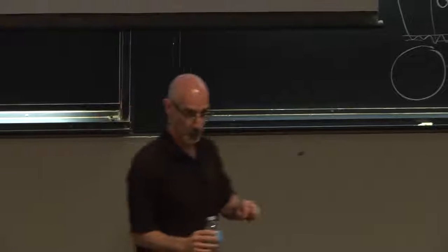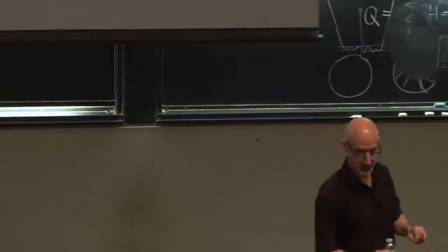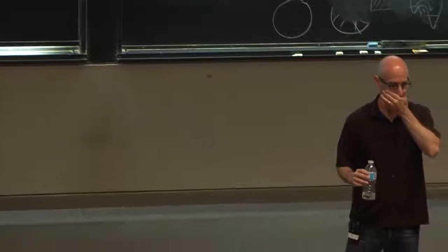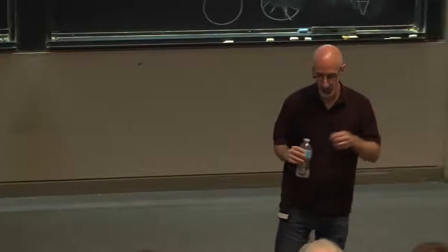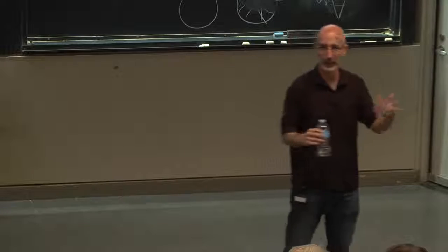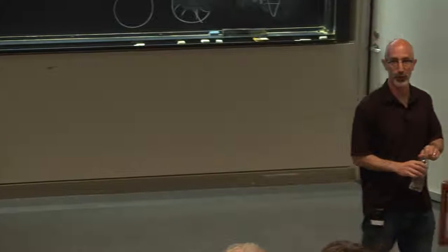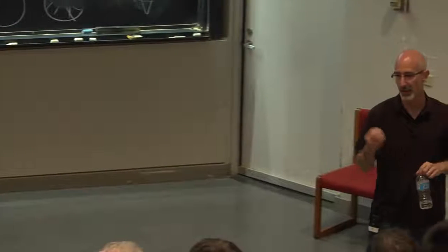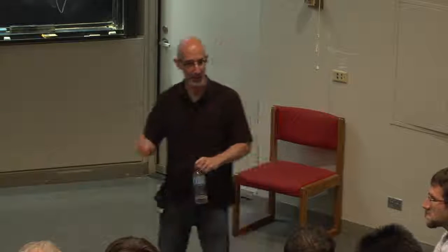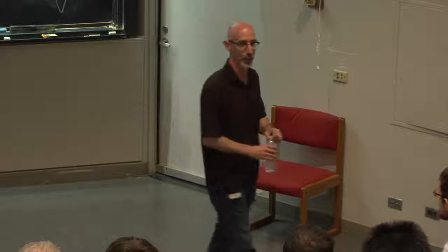So basically what you say, for example, is take a square lattice and you're only allowed to put particles on the lattice that have no more than a certain number of neighbors around them, okay? And so basically as you change the density, there are going to be fewer and fewer configurations that are allowed. And then you just make local moves, and if you have no local move that is allowed to connect the configuration, you're stuck. If you can move locally to a configuration where that configuration is allowed thermodynamically, you're not stuck.